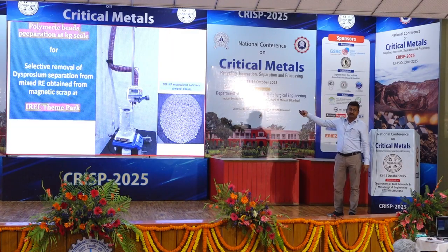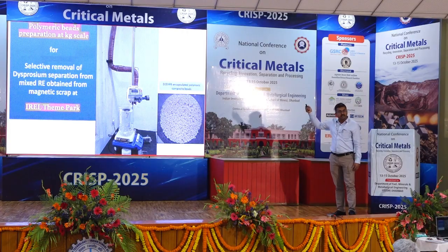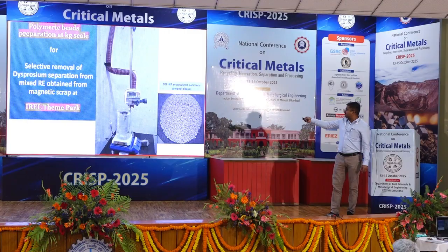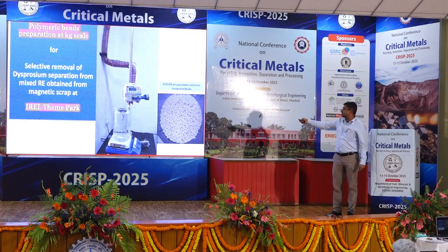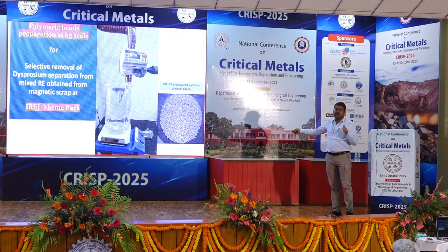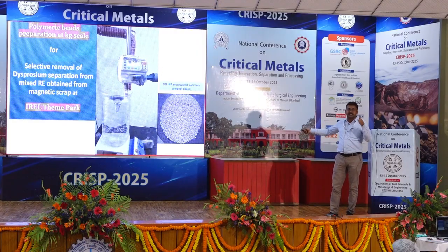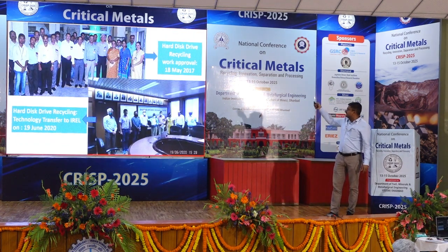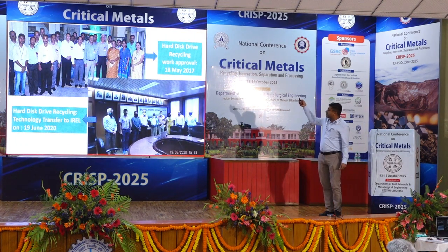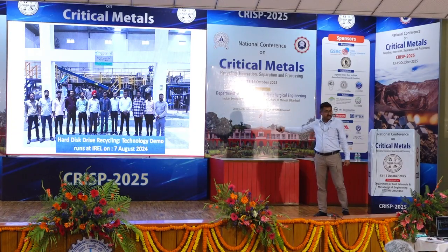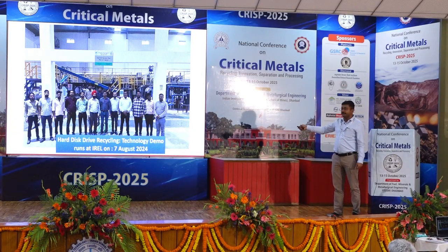And this is the setup which we have installed in IREL titanium theme park in Bhopal, and this is the method of synthesis of polymeric bead. This can be used up to 200 cycles of operation without degradation of extraction efficiency less than 5%. These are some advantages: conceptualization of the work, transfer of the technology, and finally demonstration run. All the steps have been covered till today.